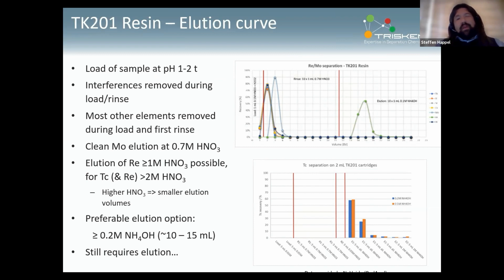Or alternatively, which might be preferable actually, you can use ammonium hydroxide, 0.2 to 0.5 molar, which are softer elution conditions that might also be more suitable for LSC measurement, but also for mass spectrometry if that would be needed. But still, there are a couple of advantages, but you still need quite a large volume to elute the technetium before the measurement, which will take quite a lot of time at the end of the day.